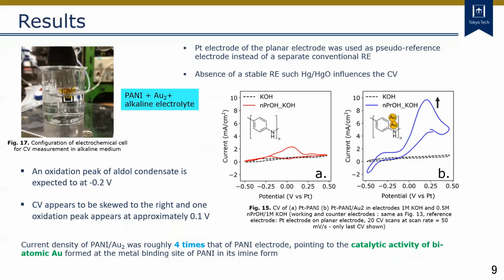The response of PANI-Au2 film towards electrooxidation of propanol in KOH alkaline medium is shown. From figure 15, it can be seen that although PANI film shows an electrooxidation peak for n-propanol in alkaline medium, in the presence of biatomic gold, the peak is enhanced to about 4 times the current density. For this experiment, the platinum reference electrode on the planar electrode substrate was used. Catalytic activity is confirmed from the electrochemical response.